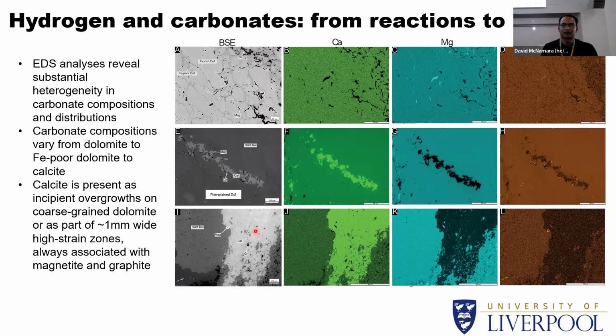But the question is, again, you have carbonates with graphite. You can form that in two ways. You can cause thermal degradation of carbonates, increasing the temperature to an extent where it breaks down into carbon and oxygen. But these samples are hosted in serpentinite, so that's not possible. The other way is by reacting the carbonates with hydrogen. You could potentially reduce a carbonate to graphitic carbon if you bring hydrogen into the system.